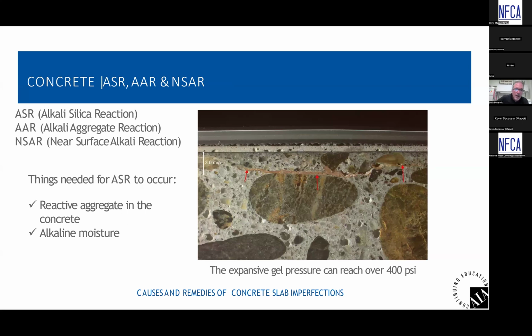Okay, another type of blistering out there is ASR, alkali silica reaction, sometimes referenced as alkali aggregate reaction and near surface alkali reaction. So similar to osmotic blisters, we need things present for ASR, AAR, or NSAR to happen. Number one, you need alkaline moisture. So yes, there's natural salts in the concrete, which are alkaline, but we need the water as a source to realize the high alkalinity of those salts. So you need alkaline water.